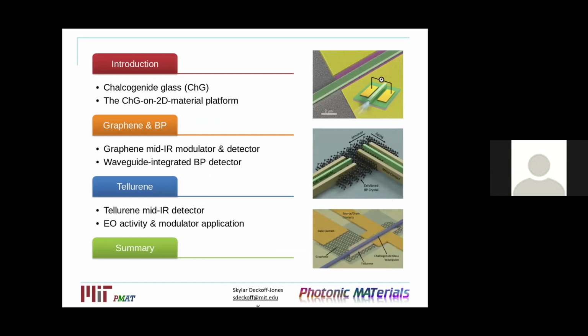So after looking at those two devices, there's a number of downsides to both graphene and black phosphorus. As we see, black phosphorus is very reactive. The problem for graphene, which I didn't go into too much detail with its use as a photodetector, is because of its zero band gap, we have high dark currents. So even when there's no light exposed, because graphene is always a conductor, you have high dark currents, which ultimately damage the noise equivalent power, like the minimum detectable signal, the sensitivity of your photodetector.